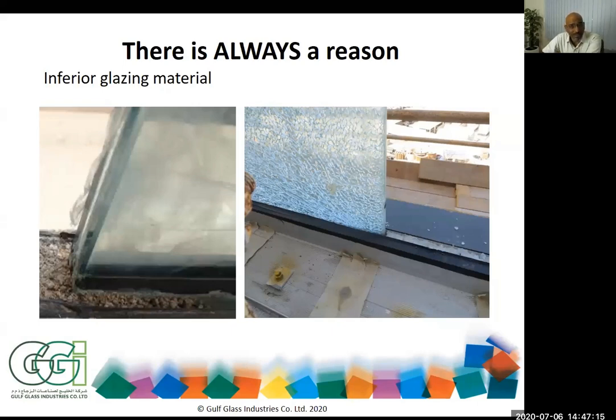Now, having known that, we had two instances of spontaneous breakage. In high wind load conditions, nearly 40 balustrade glass units broke within 3 days. We were called and told the glass is breaking, spontaneous tempered glass, broken without any apparent reason. That's what the customers always tend to say. During investigation, we found that the grout material being used was too stiff, and its hardness did not allow the glass to move in that pocket. It was not able to breathe inside that.